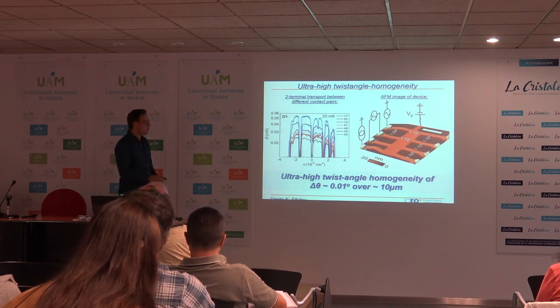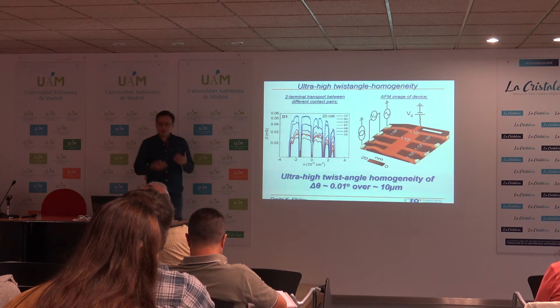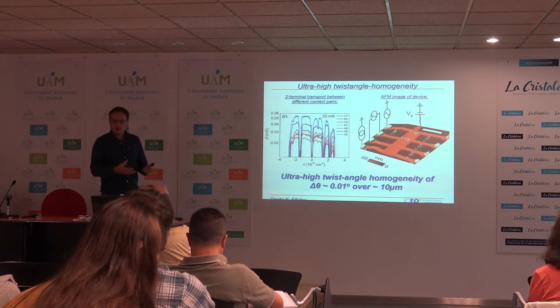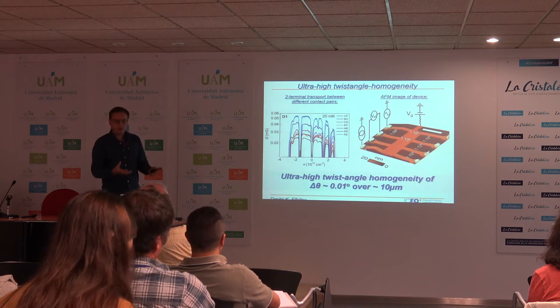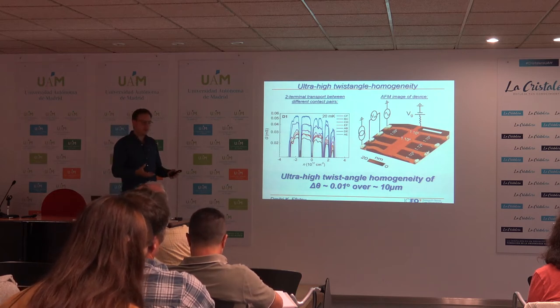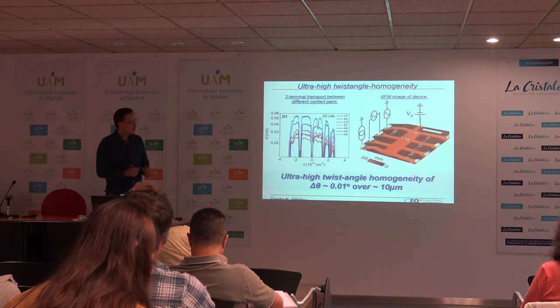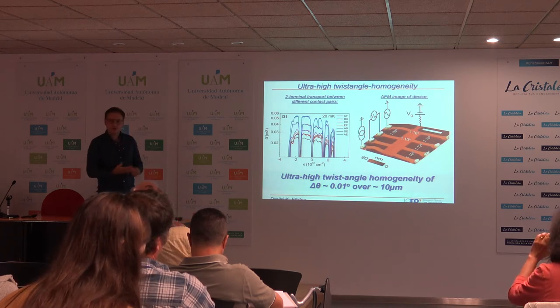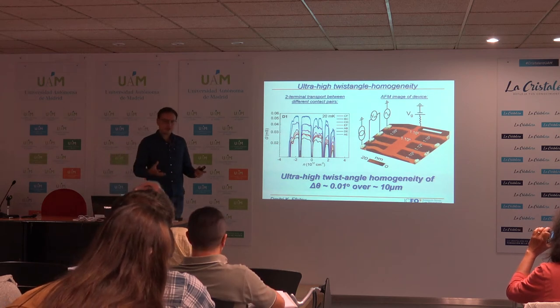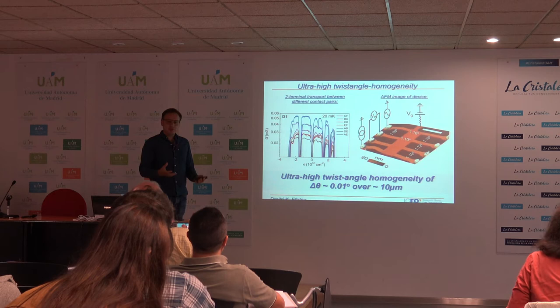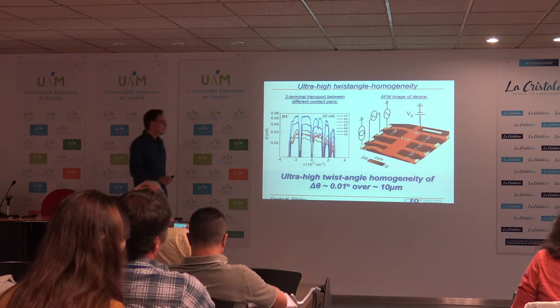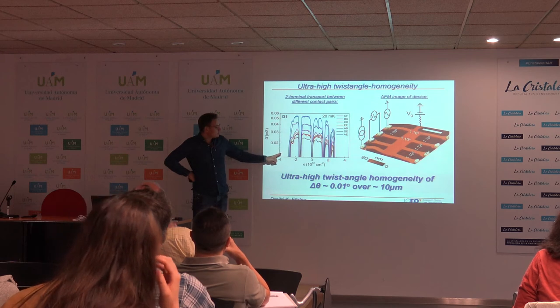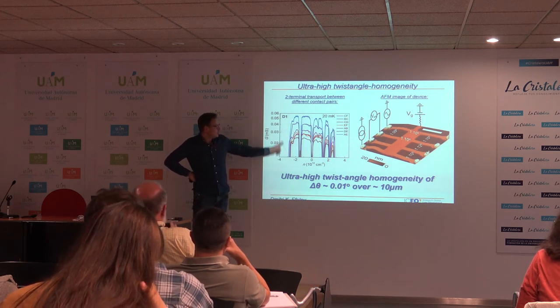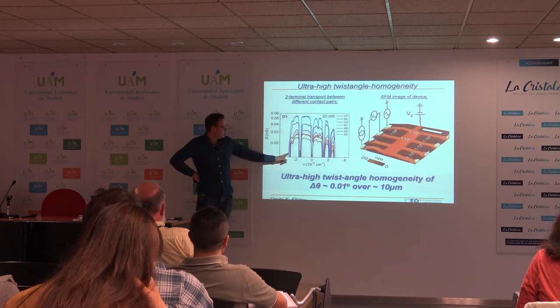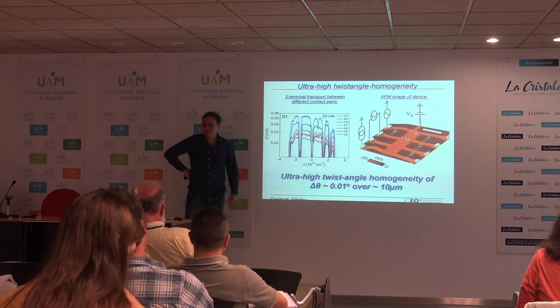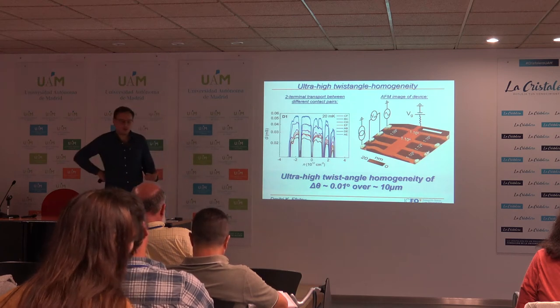This was a little bit explained in the previous lecture, but basically, depending on the twist angle, the filling of a moire band changes. Whenever we make the unit cell of a moire band bigger, since we can only fill 4 electrons per moire unit cell, that means that we need fewer electrons to fill up a moire band. So if we look at the position of the insulating dips here, in this conductance measurement as a function of carrier density, the position of these insulating dips in the carrier density tells us exactly what the twist angle of the device is.